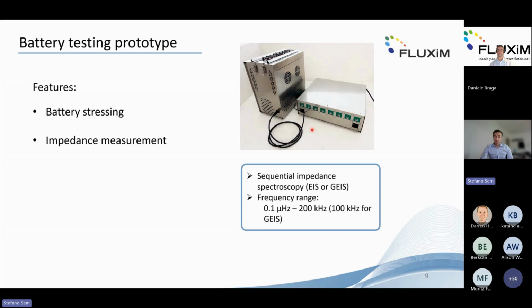Impedance can also be measured sequentially through the 8 channels. Potential impedance, so EIS, but also galvano impedance, GEIS. And the frequency range goes from 0.1 microhertz, so pretty low, up to 200 kilohertz. This is true for EIS, and for GEIS it goes from 0.1 microhertz up to only 100 kilohertz, so yeah, not the 200 of EIS.